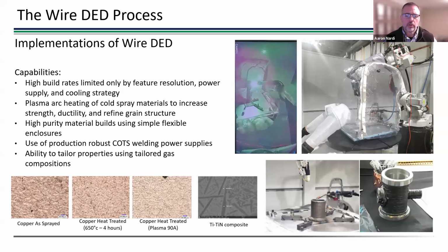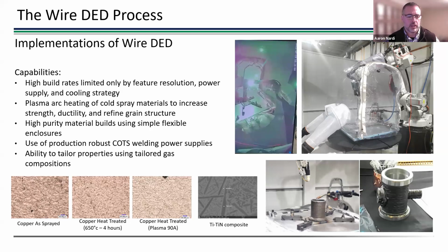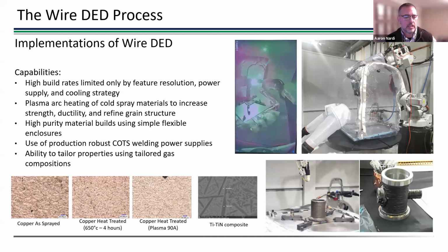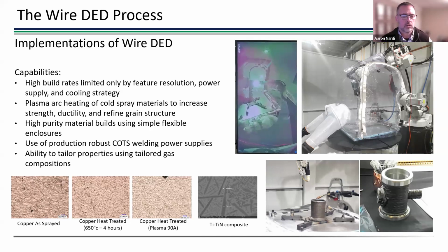We're also looking at other uses for the technology. You see examples down here where we've looked at cold sprayed copper, actually, and we've done a couple of different things to it. The first one is copper in the as sprayed condition. The second one is if you take that as sprayed material and heat treat it, using a standard isothermal heat treat.